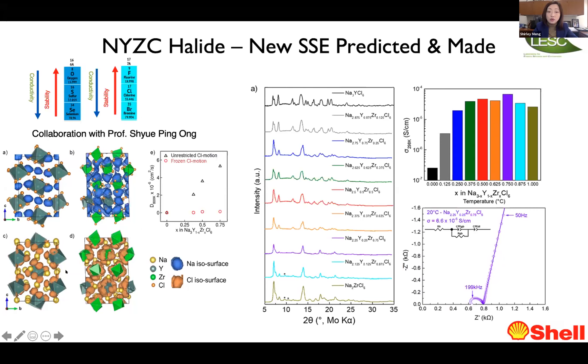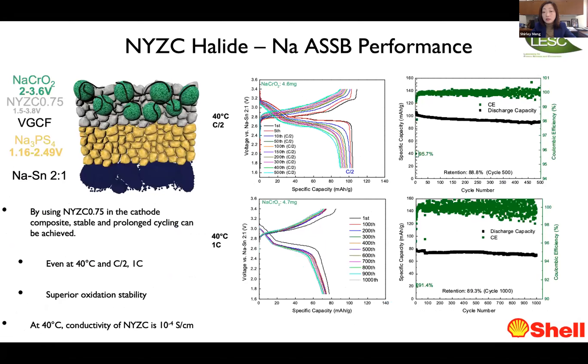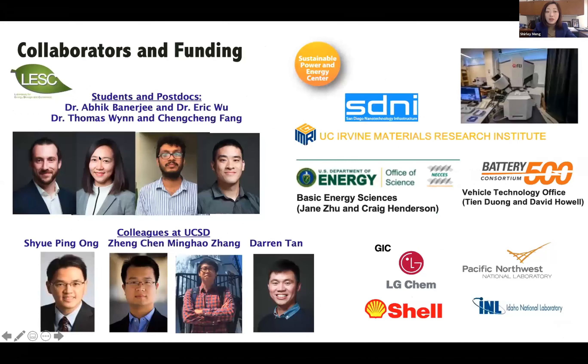We collaborated with Professor Shyue Ping Ong and found that halides work very well in sodium systems too. We report sodium yttrium zirconium chloride systems — an analog to the lithium chloride systems — achieving close to 10⁻⁴ S/cm (0.1 mS/cm), not yet as good as the lithium system but a first successful demonstration of complete solid solutions in this halide phase. Very excitingly, we report 1,000-cycle performance at 40°C using sodium-tin as the anode, showcasing that sodium solid-state batteries are indeed possible.